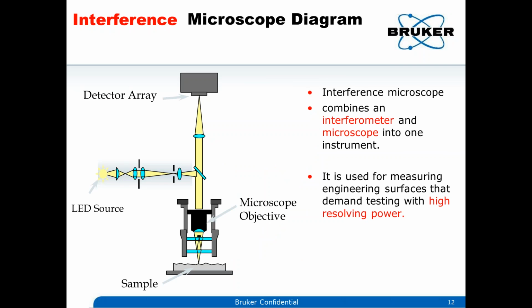That's good. So basically, if you use a Mirau objective, you have a little more detail here. You have the source, and you split it here. One goes to the reference mirror, the other goes to the sample, and then you collect them. The path difference created by the sample roughness and other things would create the interference fringes. So the one advantage of relying on interference fringes instead of just the focal depth or things like that would be the resolution is very high.